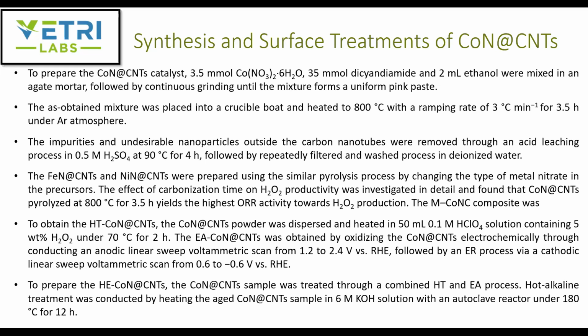So they electrochemically modified the catalyst to generate these epoxy groups. First, they did a peroxide treatment of cobalt nitrogen doped CNTs, where they dispersed the catalyst powder and heated it in 50 milliliters of 0.1 molar perchloric acid containing 5 wt% H2O2 at 70 C for 2 hours. They also did electrochemical activation to get the epoxy groups by oxidizing the cobalt nitrogen doped CNTs through an anodic linear sweep voltammetric scan from 1.2 to 2.4 V, and then subjected it to an electrochemical reduction process via a cathodic linear sweep voltammetric scan from 0.6 to minus 0.6 versus RHE.